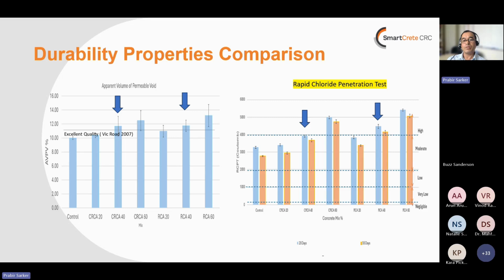On the right-hand side, we have the comparison of the rapid chloride penetration test according to the ASTM standard. We have the recommendations of very low, moderate, and high RCPT values. You can see control, then 20% CRCA and 40% CRCA, all within the moderate RCPT range, but we can see an increasing trend of the RCPT with the increase of CRCA. We can see a similar trend in the concretes using recycled C&D waste as well, but from the comparison we can see the increase is even more for recycled C&D waste as compared to the CRCA aggregates.